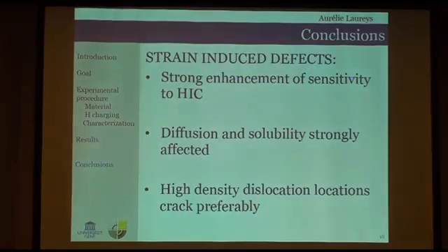So my conclusion is that the strain-induced effects strongly enhance the sensitivity to hydrogen-induced cracking. The solubility and diffusion are strongly affected, and a lot of initiation locations are induced, and also due to the high density dislocation planes, cracking occurs more easily, making cold deformed material much more sensitive to hydrogen-induced cracking than recrystallized material.